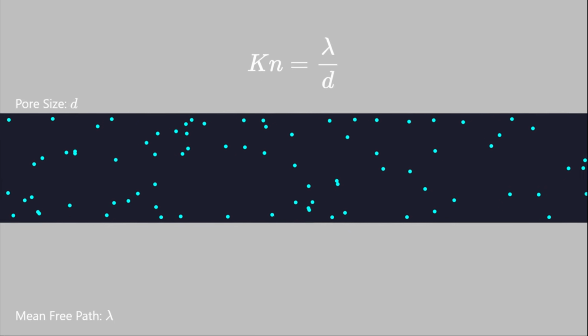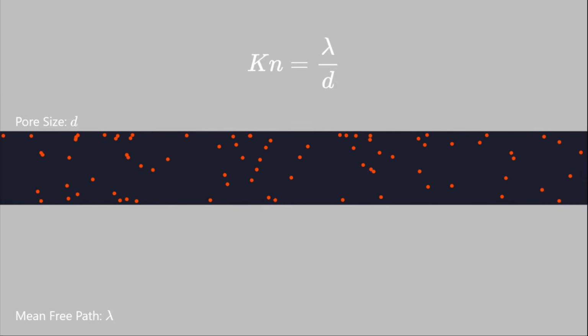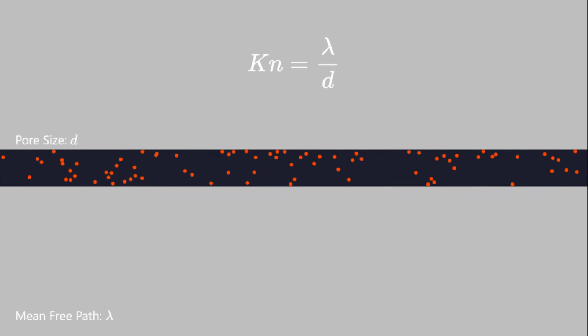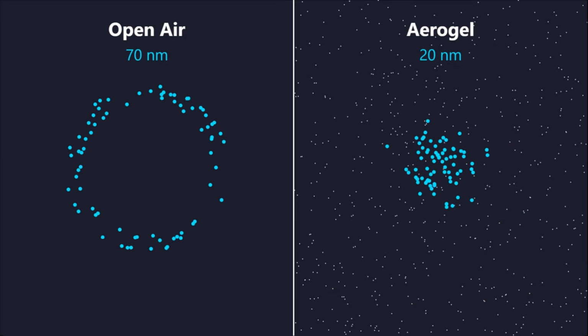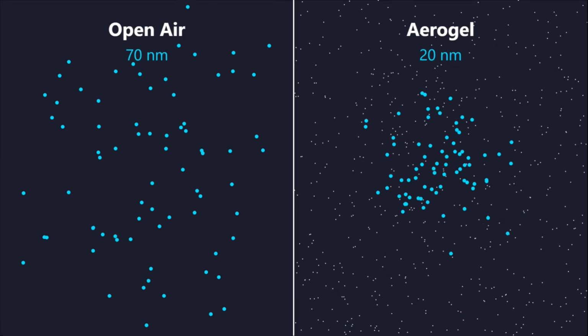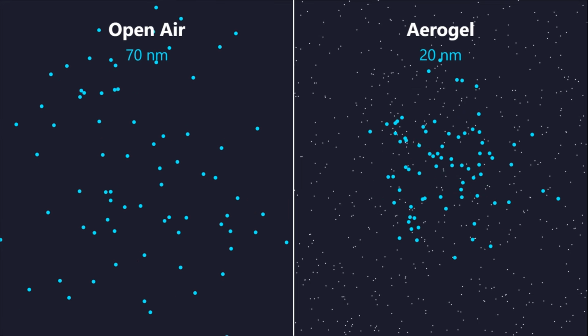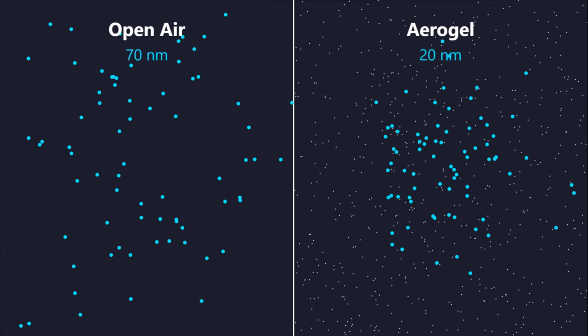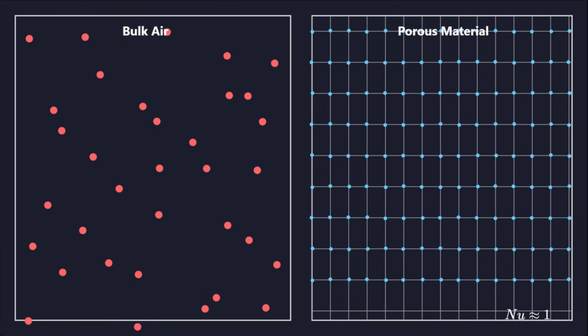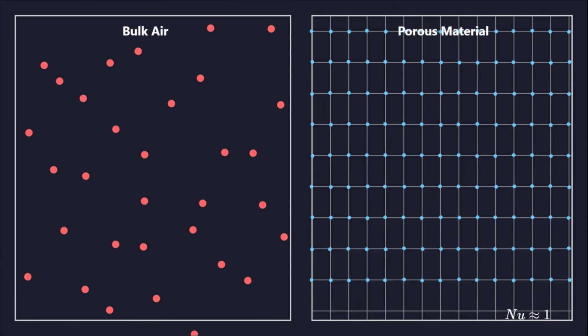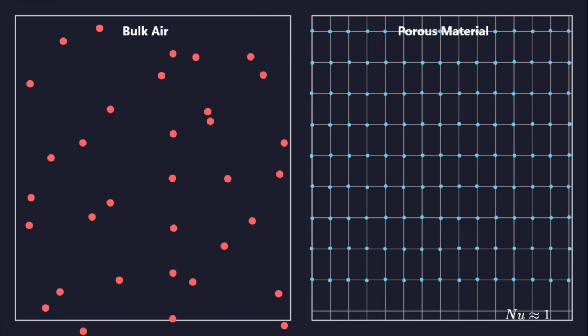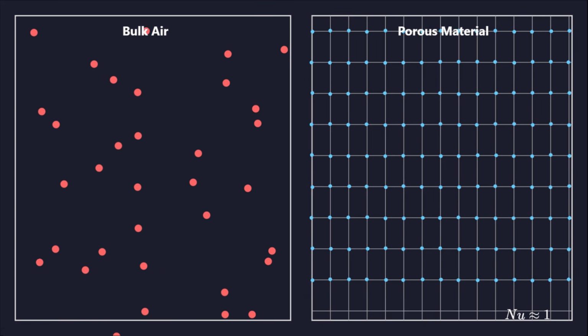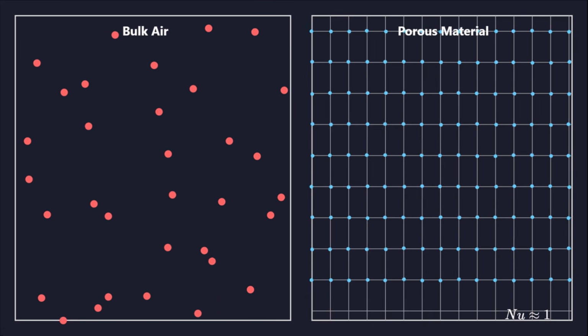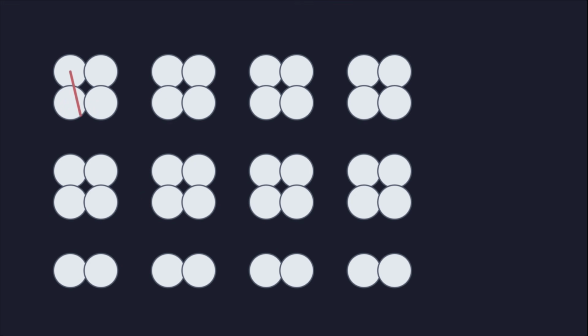The Knudsen effect occurs when the pore size is smaller than the mean free path of gas molecules, drastically reducing gaseous heat conduction. In open air, molecules travel 70 nanometers between collisions. In aerogel, they hit a wall after only 20 nanometers. Because the pores are so small, air cannot circulate within the material, effectively eliminating heat transfer through convection.